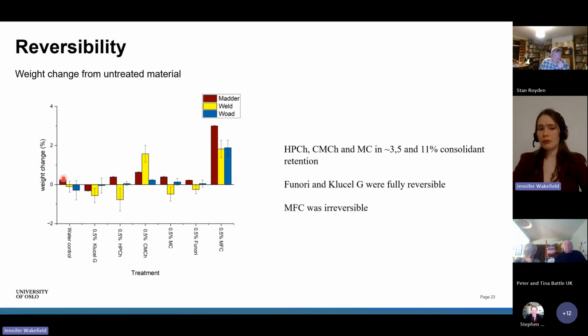So you can see there's some small variability just within the water control, but it's pretty much gone back down to zero. The Klucel G has also gone back to original weight and lost a little bit more, and that could be because some of the fibers that were loose around the edge possibly came off during the treatment or during the washing or during some of the measurements as well. And what can be seen, they're mostly reversible, particularly the Funori is very similar to the water control.